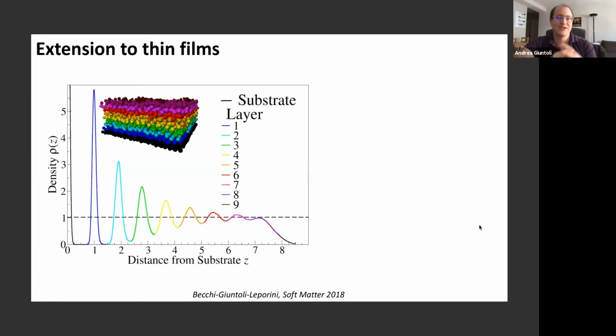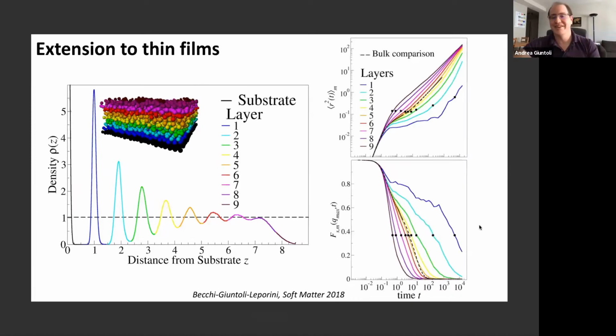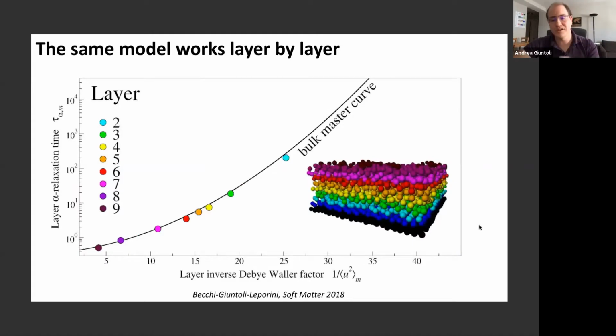divide conceptually the film into layers, which is natural. If you look at the density distribution of the film, you'll see this nice modulation of these different layers from the solid substrate to the free surface. And if you now measure, layer by layer, again, the alpha relaxation time and the Debye-Waller factor, then globally the model doesn't work, but layer by layer, you'll see a nice scaling. Using the same model as the bulk system, you'll see that each of these layers will be in agreement with that scale. And we're pretty happy about this result.